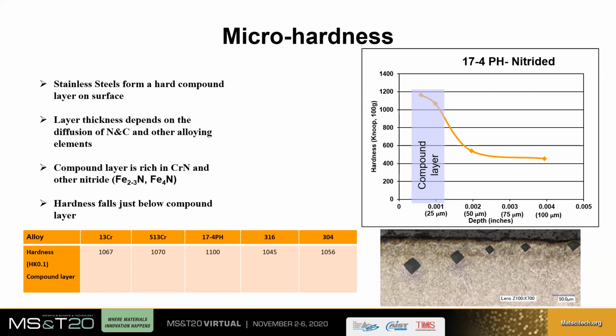Further, microhardness testing was carried out on the cross section, which is important to make sure the nitride layer is hard enough for wear resistant application of these alloys. All the materials show hardness in the range of 1050 to 1100 Knoop hardness. It is important to note that the hardness of the material falls below the nitriding layer. Here we can see the size of the indent increases as we go deeper, and from this plot we can see the surface is hard and immediately it drops to the base metal hardness.